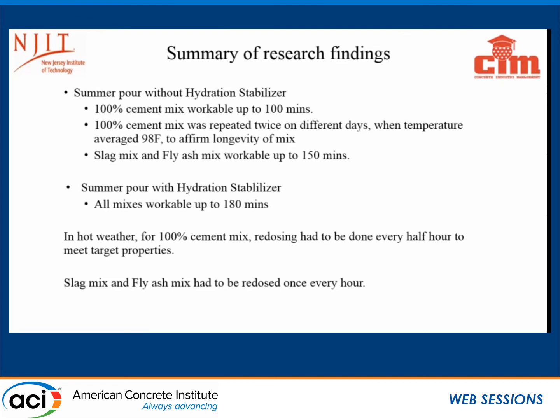All of the mixes, our control sample was the 60-minute sample. So the 60-minute sample acted as a control for all of them. The 100% cement mix was workable up to 100 minutes, after that it started setting. The slag and fly ash mixes were workable enough up to about 150 minutes. And no water whatsoever was added. No water was added at, sorry?